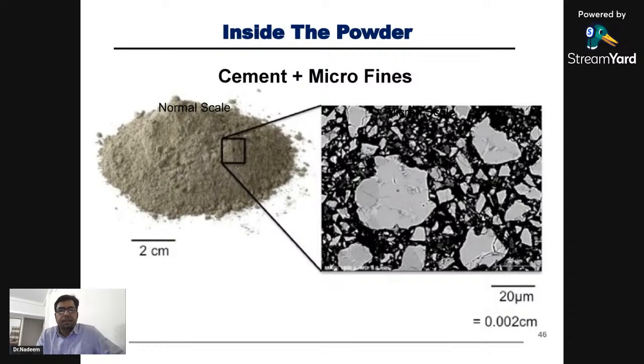In a normal size, if you see a cement particle, the average size is say 25 to 30 micron, and these are the microfine materials. So a combination of these things. If you see at a micro level, even for cement particles, a lot of voids and gaps are there in between. To fill those gaps, you naturally need a microfine material to go inside, because if you add water, water gets entrapped here and is not being used. There is an experiment: when you add microfine material inside this cement matrix, water gets taken away from this combination, and you will get a lot of flowability in that matrix. So this is the advantage of adding microfine material into a cementitious paste.